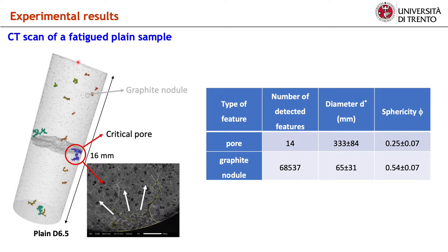It can be noted that the fatigue fracture originated from the largest pore present in the gauge volume of the specimen. In addition, pores are of much larger size and much lesser amount with respect to the graphite nodules, as summarized in this table. Importantly, in the gauge volume, only 14 pores versus about 60,000 graphite nodules were detected, displaying a mean diameter about 5 times larger and much lower sphericity and presumably higher stress concentration factor with respect to graphite nodules.